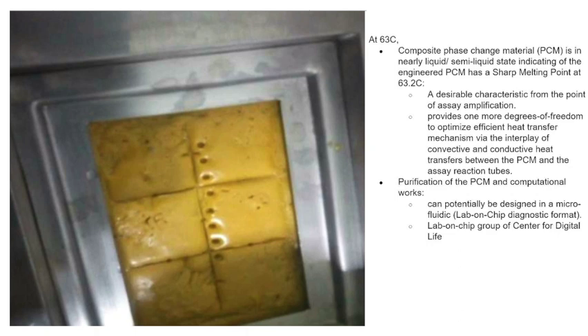We engineered a composite phase change material, which, as you can see from this figure, is nearly in a liquid and semi-liquid state, indicating that the engineered phase change material has a sharp melting point at 63.2 degrees centigrade. This is a desirable characteristic from the point of view of assay amplification, and provides one more degree of freedom to optimize an efficient heat transfer mechanism via the interplay of convective and conductive heat transfer.